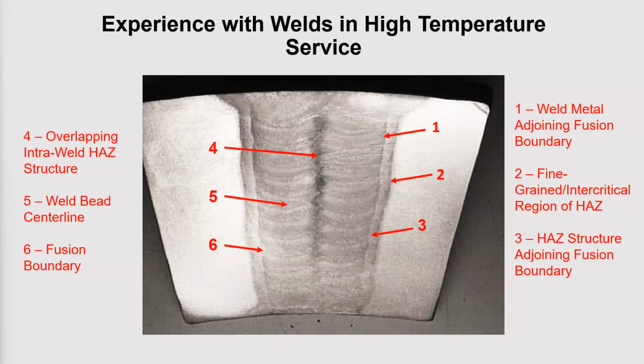what we can see, and what we have learned over the years, is that there are multiple areas in which, depending upon the particular set of operating circumstances and the particular materials being used, creep damage or creep dominated damage is likely to occur more rapidly than in other areas. And why this is important again is because when we're doing inspections on these systems, it's important to know where to look, so that you have the best opportunity of finding damage if in fact it exists. So when looking at these, the kind of areas that we know from experience can be vulnerable to premature or accelerated